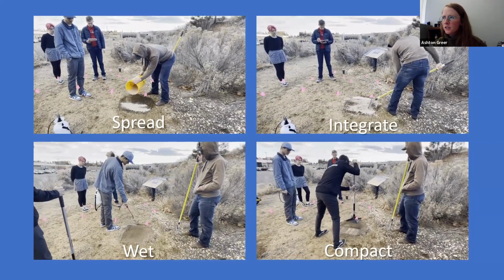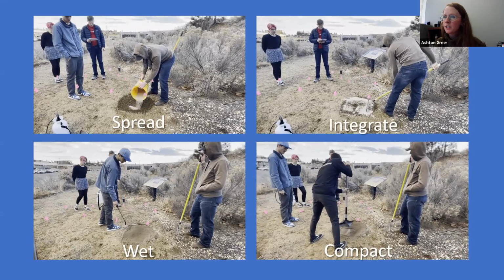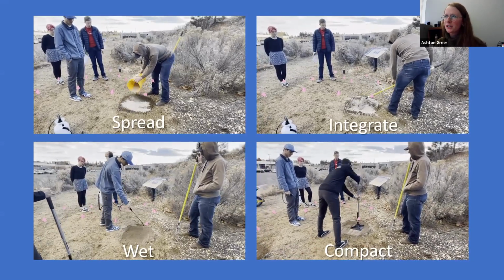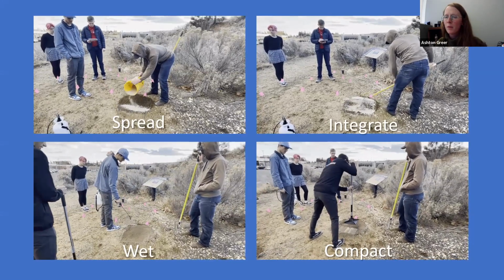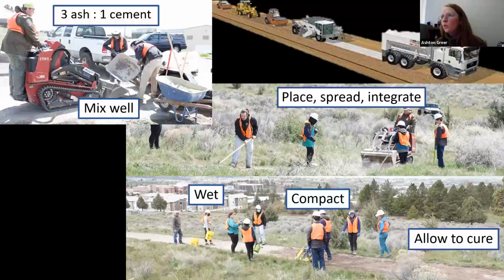So we refine these processes through small scale testing like you see here, while keeping in mind that in most applications, we would probably need to be applying the surface over a much larger area. So when we applied our treatment to the Geo Trail last May, we mobilized a crew of about 20 student volunteers and kind of drew inspiration from the convoys that we typically see in roadway construction. So we mixed our dry materials on a much larger scale and used a small front end loader instead of 5-gallon buckets to transport the mix to different areas of the trail. I think we ended up doing about 33 trips back and forth along the trail. Of course, those trips got shorter and shorter the more progress that we made.